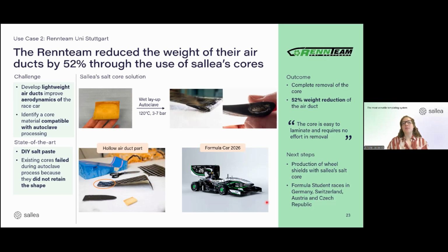I think the biggest learning, or what they were mostly excited about, is that they managed to achieve a 52% weight reduction of the air ducts compared to before. It was also possible to remove the core fully. And they let us also quote them. So they said the core is easy to laminate and requires no effort in removal. So with them, the next steps are that we actually produce additional cores for other parts for the race car. And then they will actually go to some races in Germany, Switzerland, Austria, and actually even also the Czech Republic. So also a very successful project.